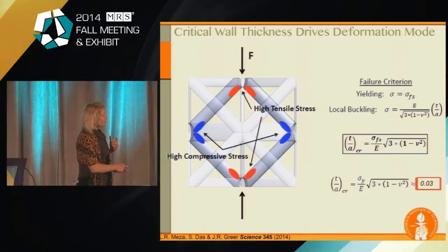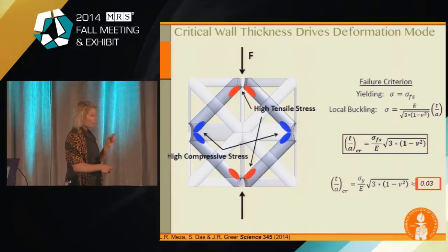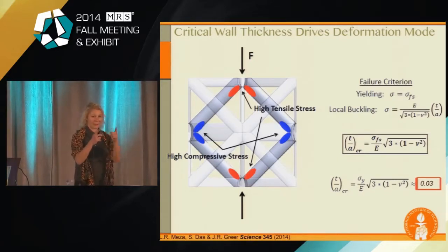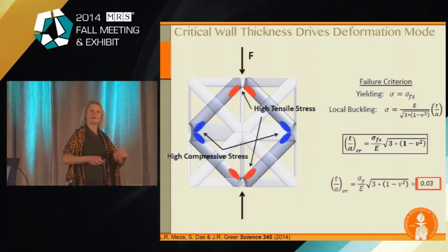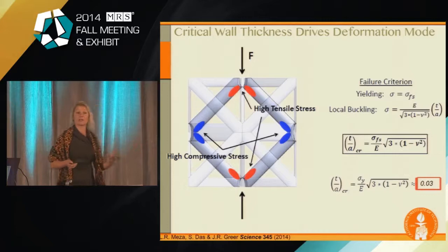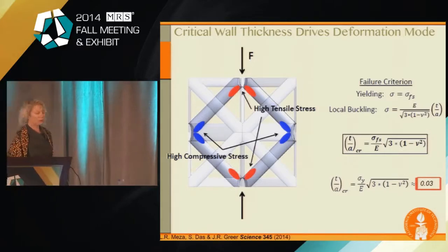Now, there's a competition of these two modes, and it turns out that there's a critical ratio between the wall thickness and the radius of the tubes that comprise the nanotruss. If that critical ratio is about 0.03 and below 0.03, the structure is going to be able to buckle, and so the entire deformation will commence smoothly, and then we'll be able to recover. And if it's above that ratio, then it'll be catastrophic. So let's see if this is actually what happens.